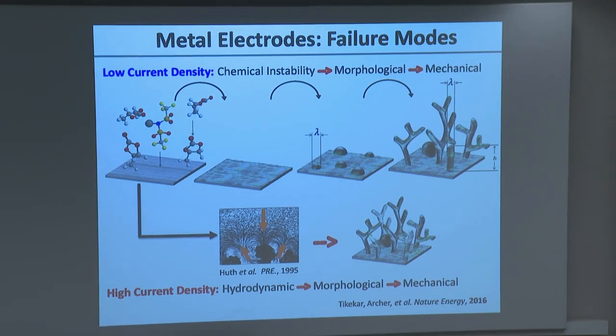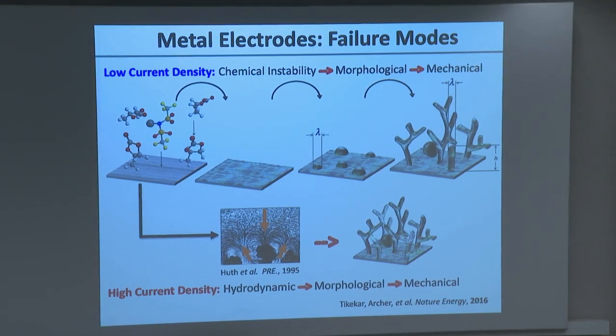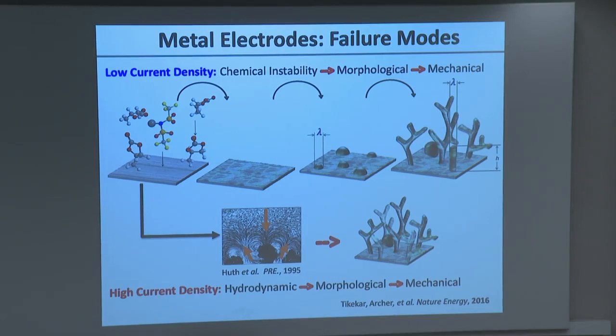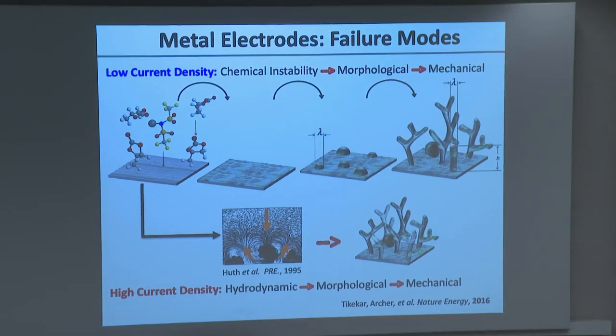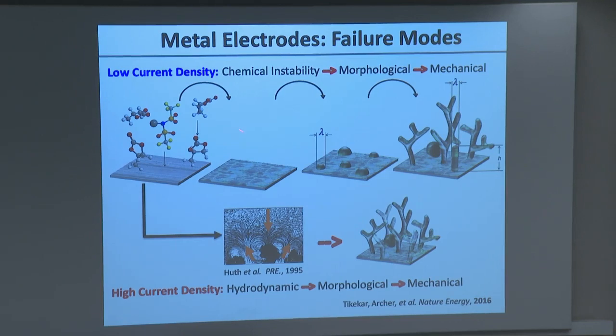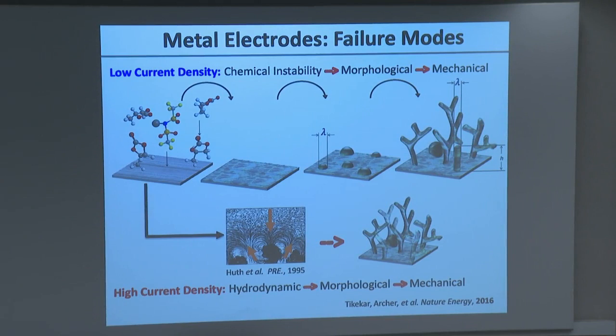At low current, it is thought that what occurs is that first the metal, be it lithium, sodium, aluminum, reacts with the electrolyte that's present in its vicinity to form what's called a solid electrolyte interface. So this is a new material that results from the chemical conversion of the electrolyte in contact with the metal. The trouble is that for reactive metals, they're quite eager to participate in these reactions. And so the end result is that they react everywhere they touch the electrolyte. And the consequence is that you have this sort of patchy SEI, a heterogeneous interface.